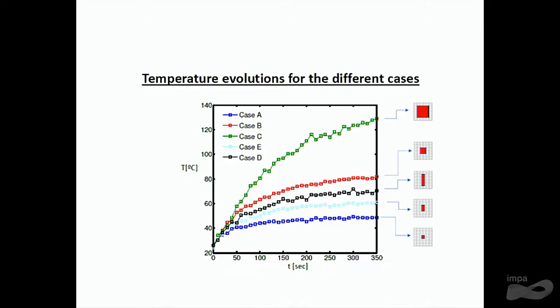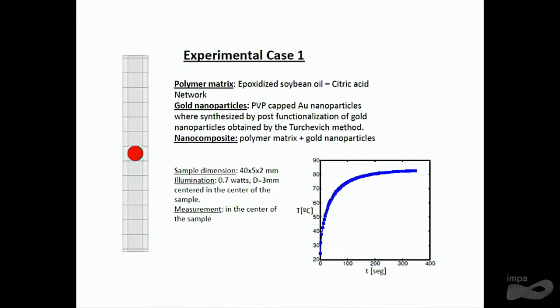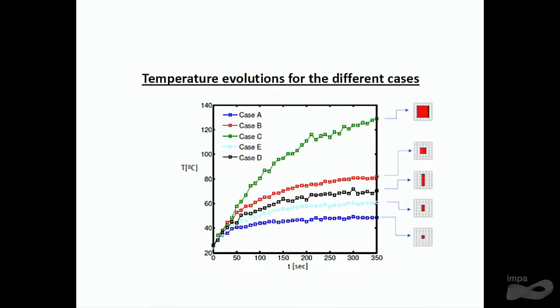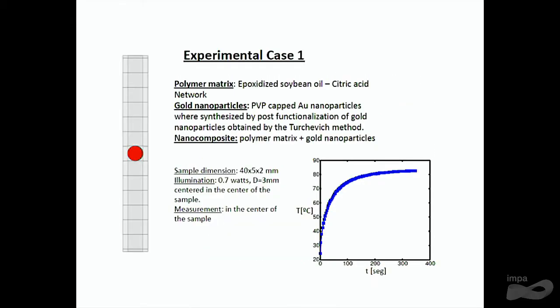As a summary of what I showed before, this is the evolution of temperature for each case. The cases are the ones that are here. As you see, temperature evolves in a different way depending on how you illuminate the sample, and reaches temperatures that are quite different. We also analyzed, so those were the experiments run in a simulated way, but we also run a couple of experimental examples.